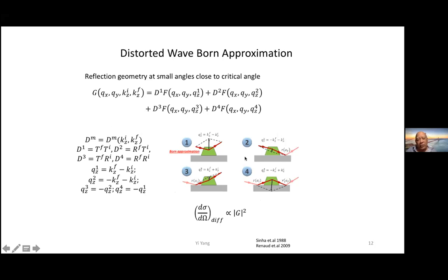At least one of those processes involves scattering off the substrate. And it's these processes that mess up the simple Born approximation. Single scattering from the sample gives you the Fourier transform, but these processes give you extra speckle or destructively interfere with these and mess you up.